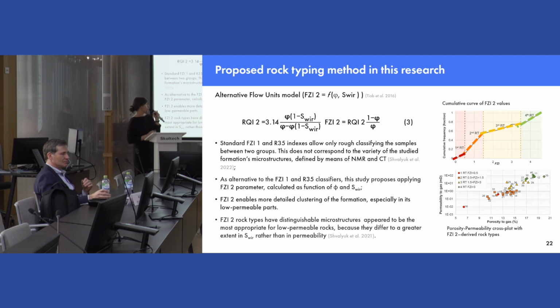And for this clastic formation, I proposed an alternative flow zone index, which is calculated as a function of porosity and irreducible water saturation. So standard classifiers, which I mentioned above, are functions of porosity and permeability. And these techniques, unfortunately, didn't provide a good match between the core-derived rock types and the microstructural study, which was defined by nuclear magnetic resonance and computed tomography. And also, I need to say that these techniques mainly separated the formation into siltstones and sandstones.